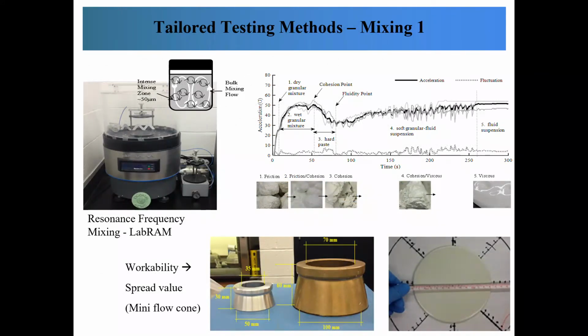For example, mixing. In the first phase of paste development, we used a resonance frequency mixer due to its high mixing consistency, short mixing time, and quality of particle dispersion, without the use of any mechanical mixing tools. At the top right, you see an acceleration versus time diagram, complemented by pictures showing the change from wet particle clumps to a homogeneous UHPC paste mixture. Due to the limited mixing volume, a mini flow cone was designed and used for measuring the spread.